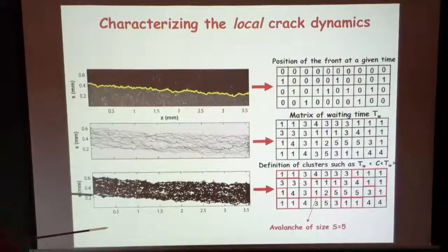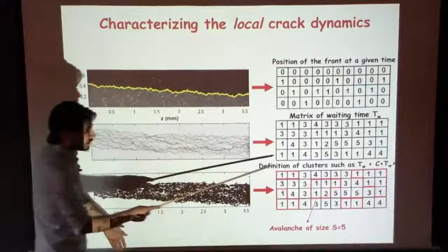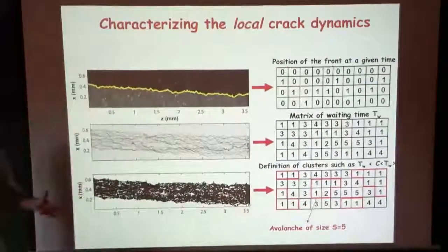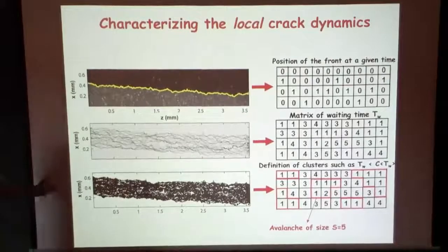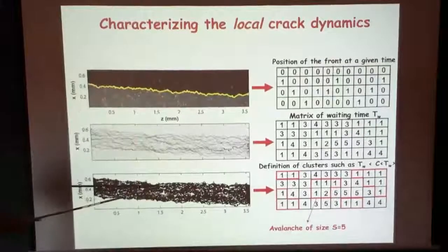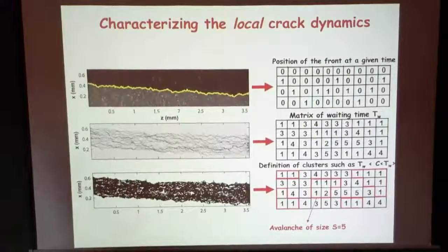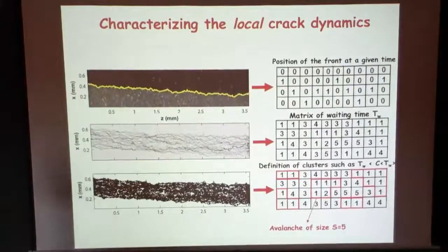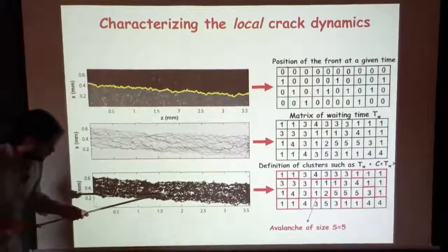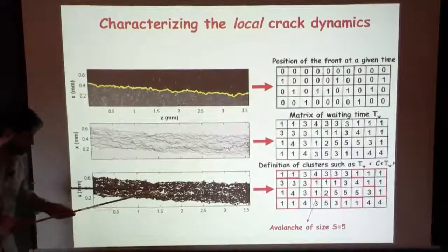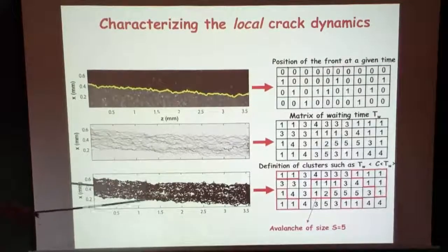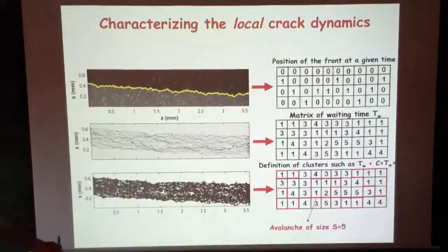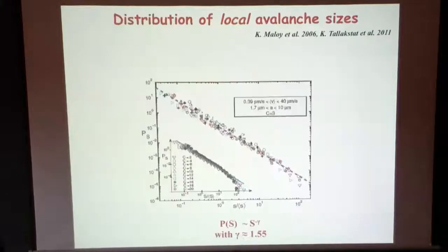And then you can threshold it, saying, okay, I keep only waiting times smaller than some threshold that is a few times the average waiting time. So in white, I have zones where the front has spent very little time. In other words, in this zone here, the front has moved from this location to this one. So it defines clusters that you can define as avalanches.